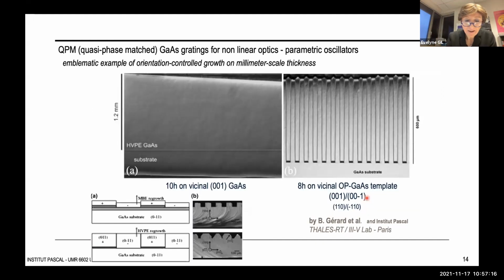Another emblematic example of orientation controlled growth on a millimeter scale thickness is the synthesis of quasi-phase matched gratings for nonlinear optics. As a matter of fact, HVPE is able to keep an original alternate orientation, 001 and opposite 00-1, all along an 8 hours growth, which is necessary to produce the half millimeter thick template suitable for parametric oscillator applications. Maybe for the young audience, these structures are used to convert a laser frequency into another by taking advantage of optical second order effect.